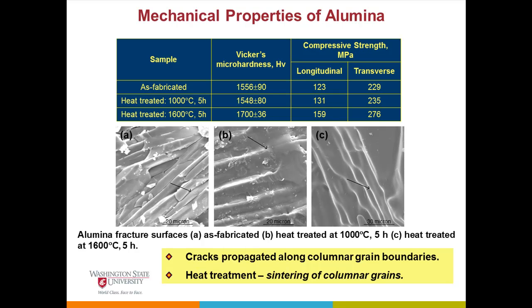Once we are done heat treating, we're not changing much in hardness, 1556 to 1548, almost no change. But at 1600, there's definitely a change, and the difference is lower. You can see this from the fractography. This is the fracture surface of the as-processed sample, this is the 1000 degree heat treatment, and this is 1600.